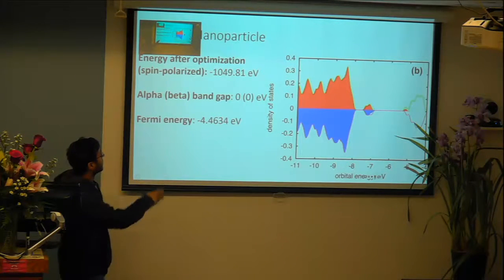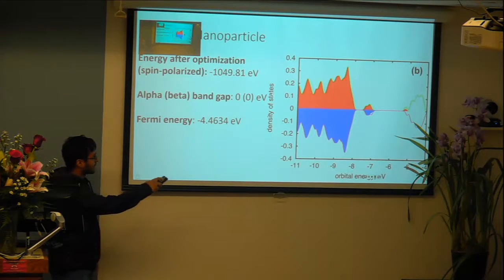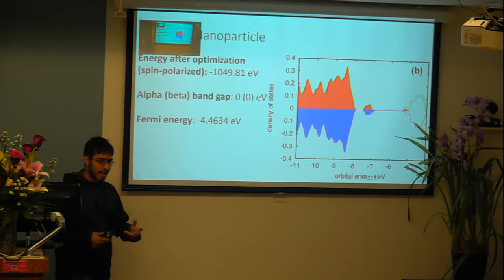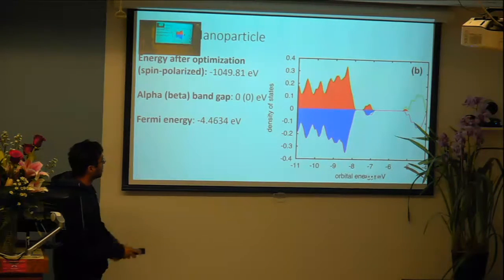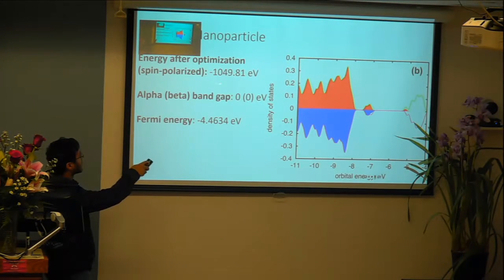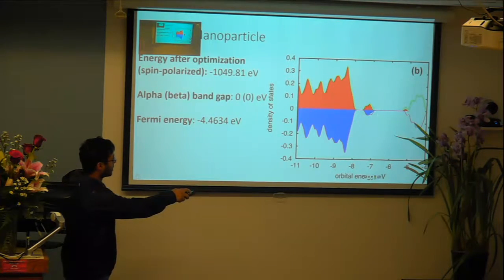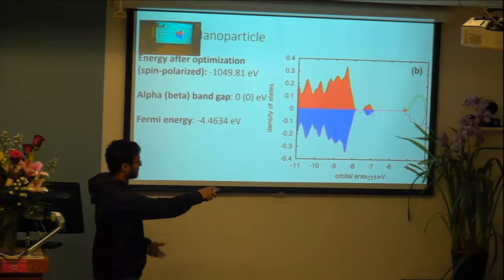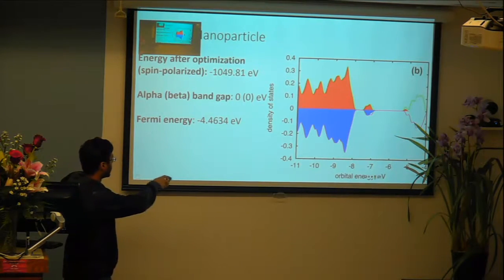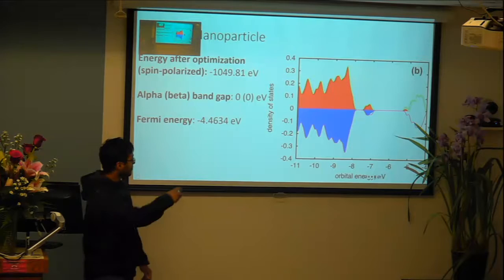Here on this slide, this is the density of states for the silver nanoparticles. So we did optimize this model 5 times. And you can see, again, the energy after optimization as well as alpha and beta band gaps. You can see that there are, again, electrons in the conduction band. And finally, Fermi energy as well.